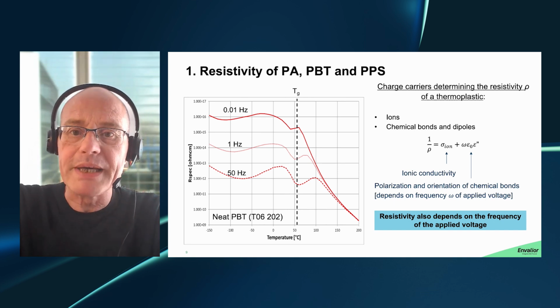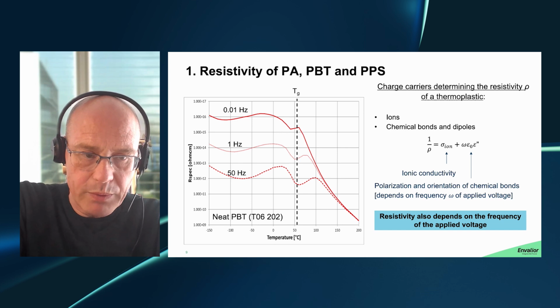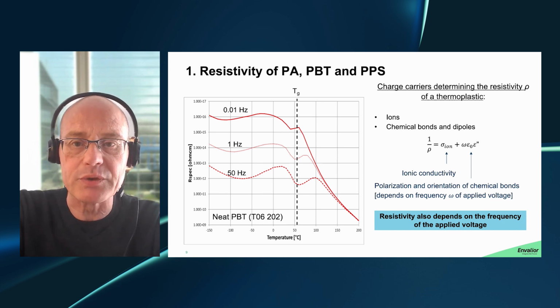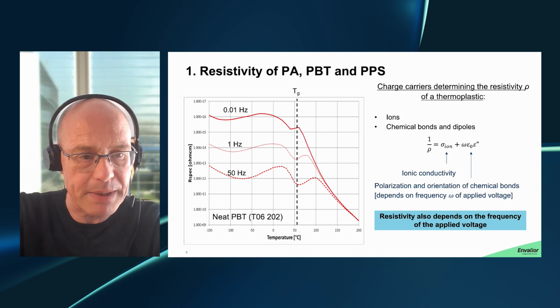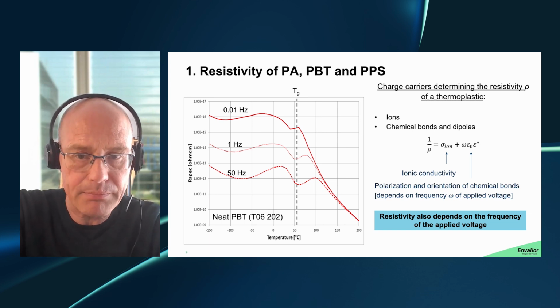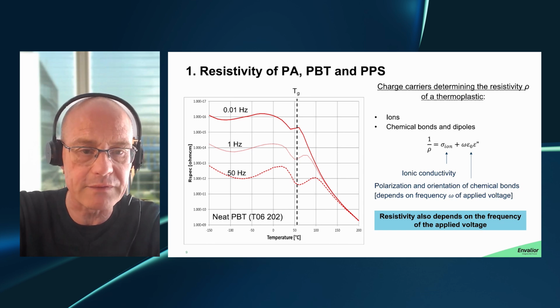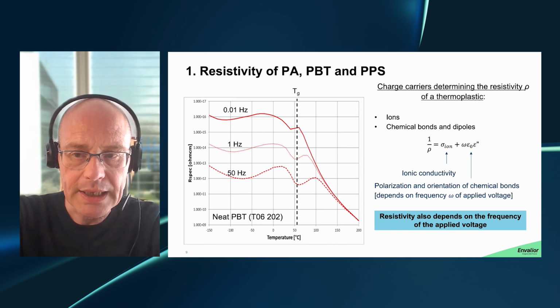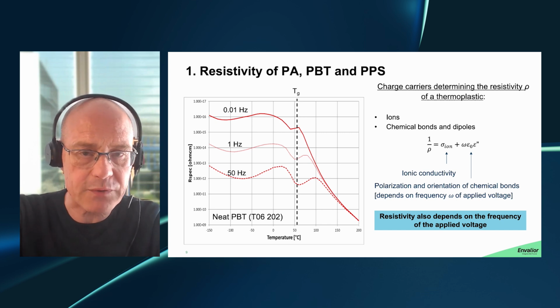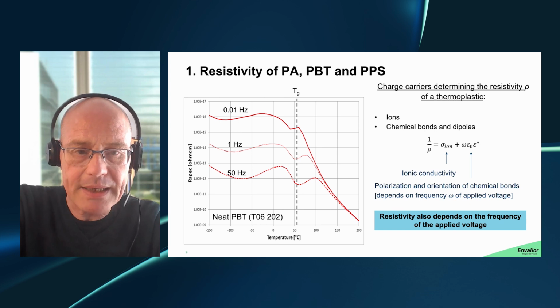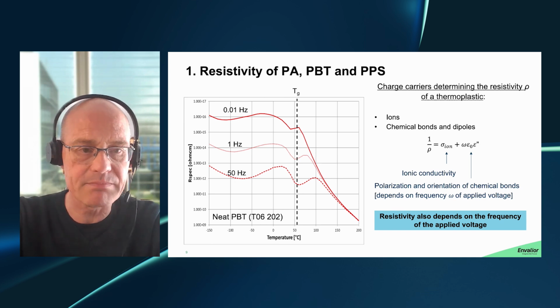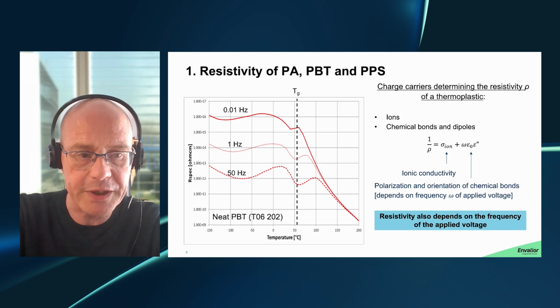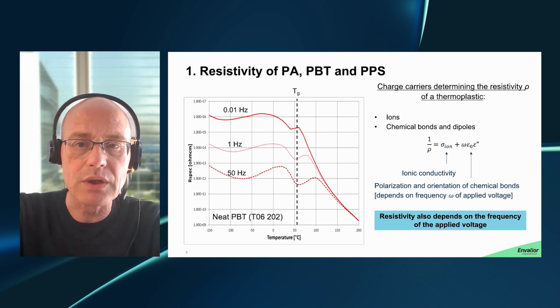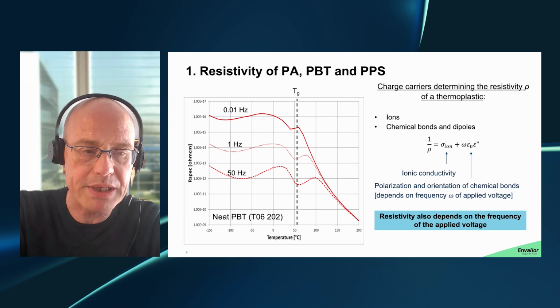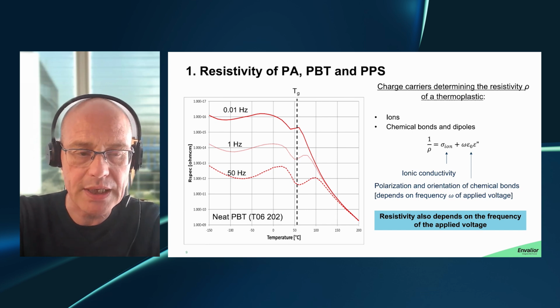This is important because what we want to explain here very briefly is that the resistivity of the polymer does not only depend on temperature and relative humidity, but it also depends on the frequency of the voltage that you do apply. It's easiest understood as follows. Basically, in a polymer, there are charge carriers, such as ions that may stem from the flame retardant that you feed to the polymer or from the stabilizers that you feed to the polymer. But there are also chemical bonds that carry charge. So basically the chemical bonds that constitute the molecules.